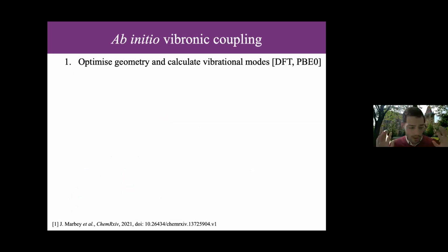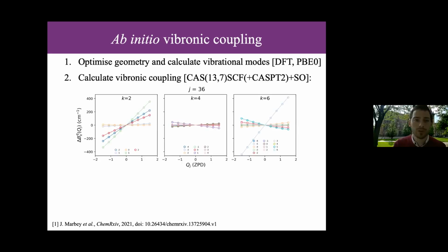And so we've done more or less exactly the same thing as I talked about before to calculate the vibronic coupling. Optimize geometry, calculate vibrational modes. Then we distort the molecules, and here I'm just showing you how the crystal field parameters of the ytterbium are changing as you're distorting along a particular vibrational mode. And so again, we use CAS-SCF. We've done a few more special things here, but that's a detail.